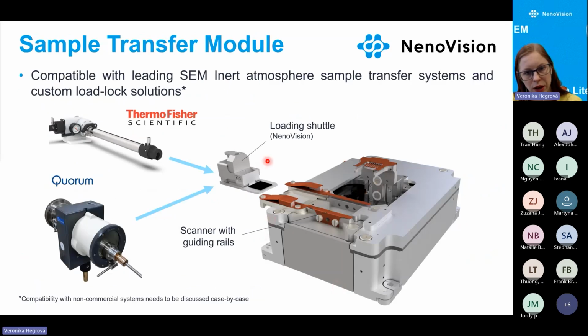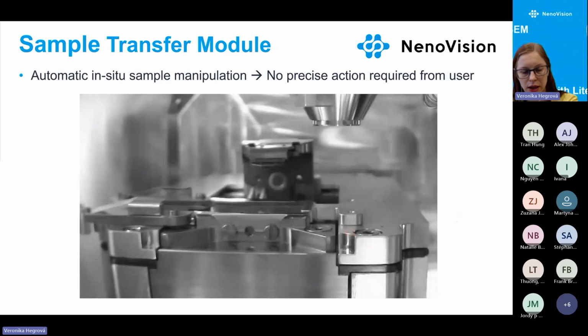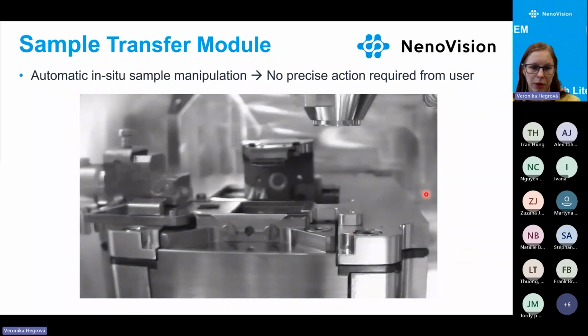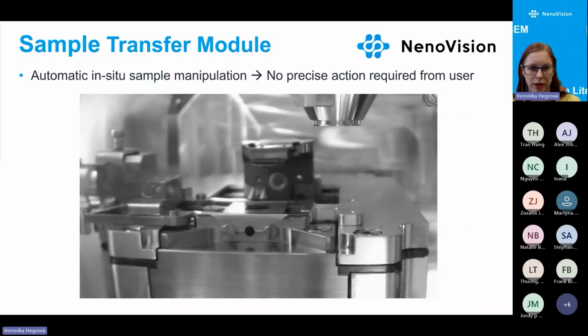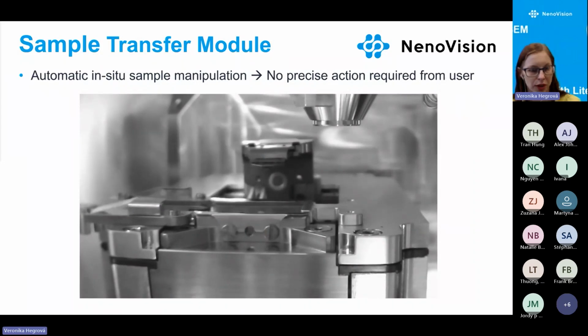So we have Lightscope, and we have the sample transfer module, which is crucial to transfer the sample without touching air humidity. We have the loading shuttle and the rails for the sample to get exactly to the location where it should be, in the middle of the scanner, and then we can start analyzing and see how it looks in the SEM. So we have the sample in, and then we take the sample out. It's fully automatic, so there is no precise action required from the user.